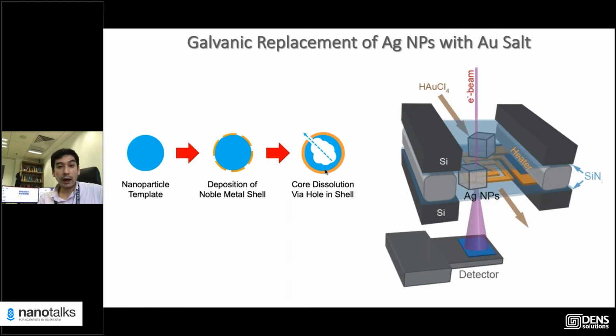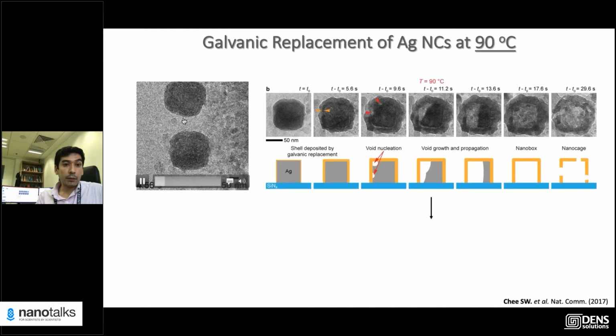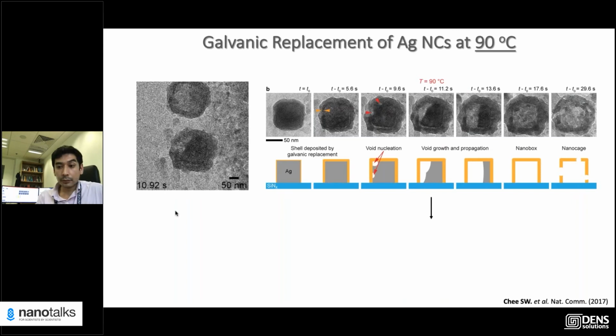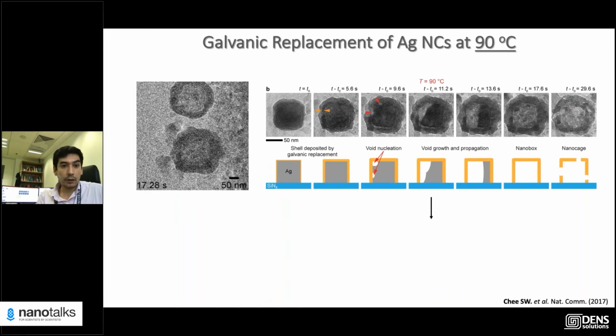So we wanted to see how silver nanoparticles corrode when we introduce a gold chloride solution, and see how the galvanic replacement reaction actually proceeds. So here's the movie of what's happening. Let me see. Okay, so I have to go a bit faster.